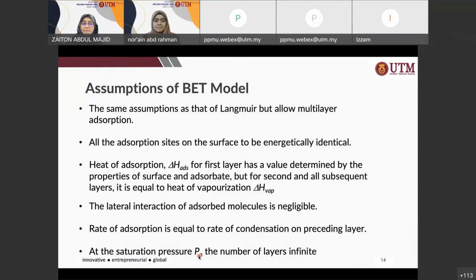Unlike the Langmuir, which assumes one monolayer and that's it, at the saturation pressure of P0, P0 is normally taken about 1 bar. So your relative pressure P over P0 is about 0.99 or about 1, very close to 1. So at this saturation pressure, the number of layers is infinite. You can have many, many layers.